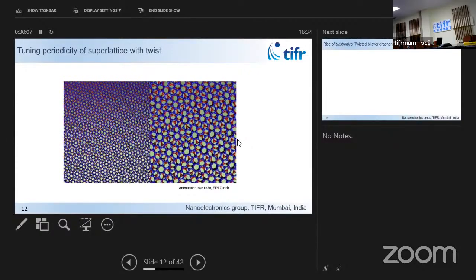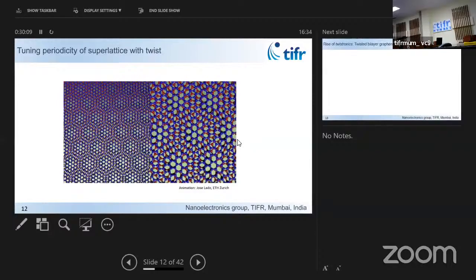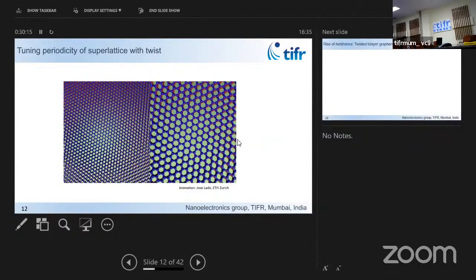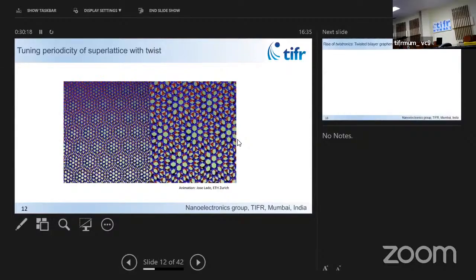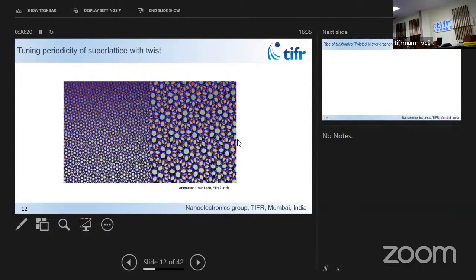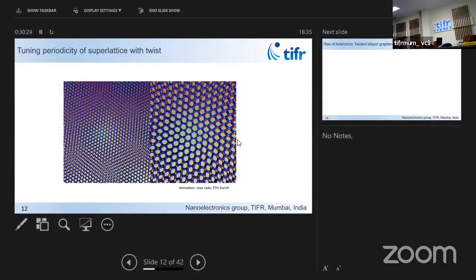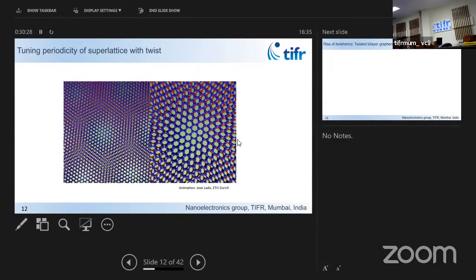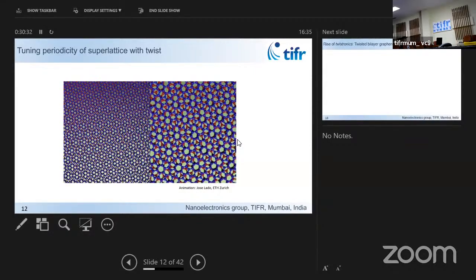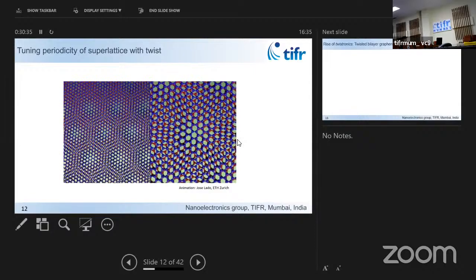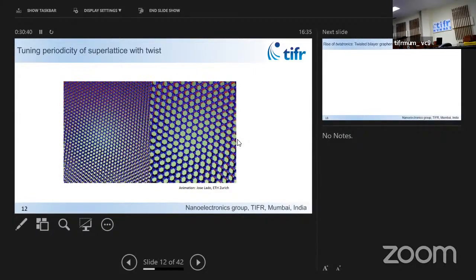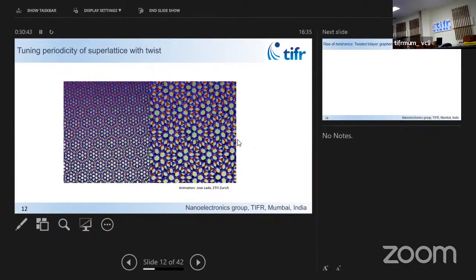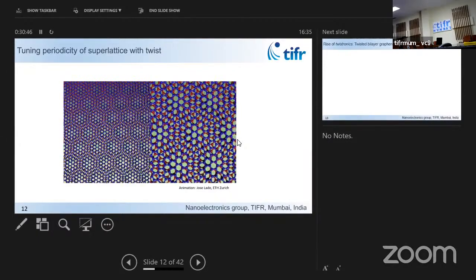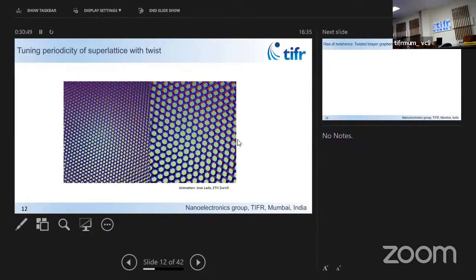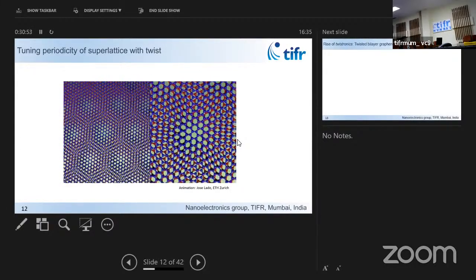If you have one two-dimensional material, you put another two-dimensional material on it at a relative angle. You have the original atomic lattice, but the twisting angle controls the next level of periodicity that you get. This is called the moiré periodicity, and you can think of it as scattering of the electronic wave function. It modifies the overall system's electronic properties. It's no longer equal to just the two layers of the material. So it's the same trick of a superlattice to modify electronic properties, but it's a fundamentally different way of twisting, and that angle control is a radically powerful tool for controlling electronic properties. I'll give you a glimpse of that.